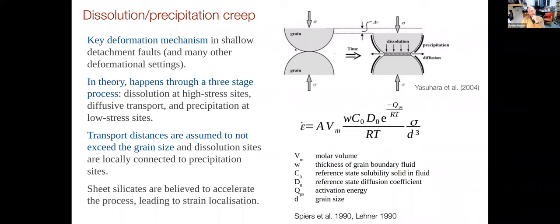It's pretty simple, actually. The theory is that if you have two grains here touching in a point contact, you have a very high contact stress here. And that feeds back on the solubility of the salt. So locally, because solubility is also a function of pressure, if there's a fluid film sitting on that interface, the solubility will locally rise due to that contact stress. More material will be dissolved right here. A concentration gradient will emerge, and material will start to diffuse away from here, and it will re-precipitate at the earliest opportunity. That's the theory, right?